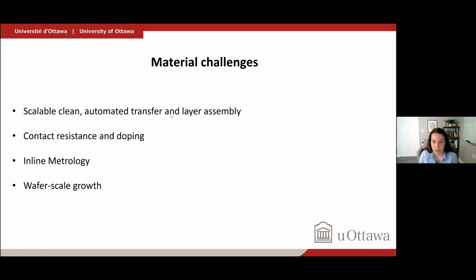One big material challenge in this field is to have scalable automated transfer and layer assembly. Big challenges around proper layer assembly in heterostructures. Others have to do with contact resistance, especially as it relates to semiconductors, controlling the Schottky barriers and so on, as well as doping, understanding the nature and the amount of doping in these materials and the defects. Another big issue as we look forward to using them in application is designing inline metrology tools, as well as, of course, wafer scale growth.